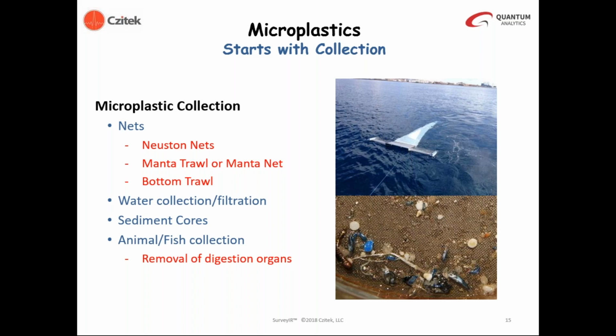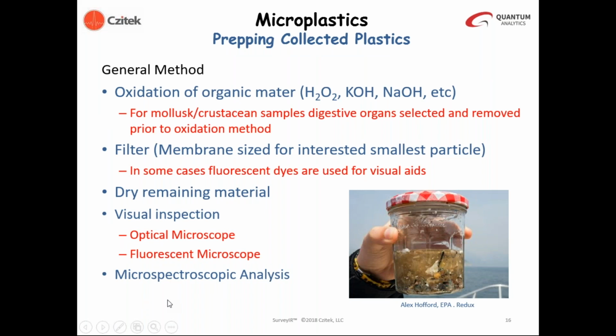And then in the case of animals or fish, we remove the digestive organs, and then we actually have to do some preparation to remove the organic material from the animal. And that is typically done with these animal samples with very caustic agents, including hydrogen peroxide solutions and hydroxide solutions. So we have some examples in our presentation here of mollusk and crustacean samples where we utilize this type of method to digest the organic material.